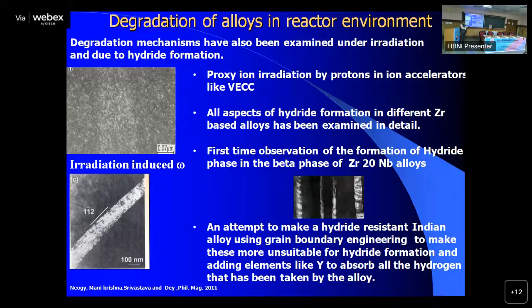The beta phase will transform to omega, and that is not desirable at all. So that information is also there with us. Then the other mechanism of degradation is hydride formation. Various types of hydride formation take place in zirconium-based alloys. We have mastered all the possible types of scenarios, delayed hydride cracking, and hydride reorientation on all the issues in single and two-phase zirconium-based alloys.